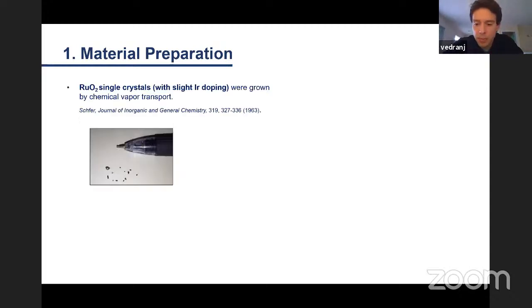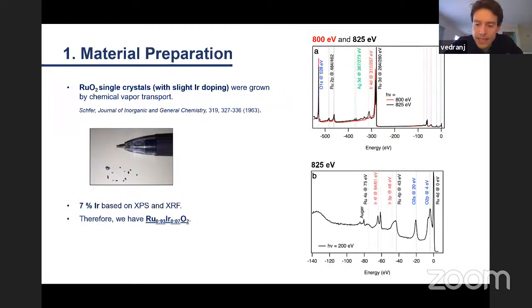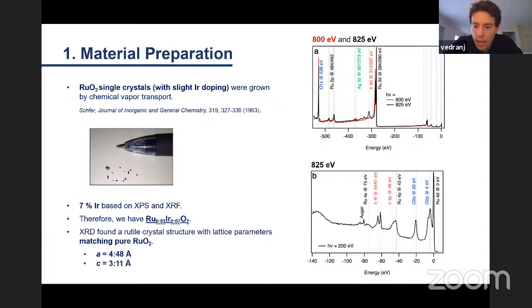So let's take a look at the material itself. These were slightly iridium-doped ruthenium dioxide single crystals grown in Lausanne by the group of Helmut Berger. They followed a recipe described for a long time in the literature, and if you follow this recipe, you will get single crystals of ruthenium dioxide in about 2 weeks. Core level XPS studies at several different energies confirmed the stoichiometry of the material, that we indeed have slightly iridium-doped ruthenium dioxide, and X-ray diffraction confirmed that it's in the rutile crystal structure, with lattice parameters consistent with rutile RuO2.